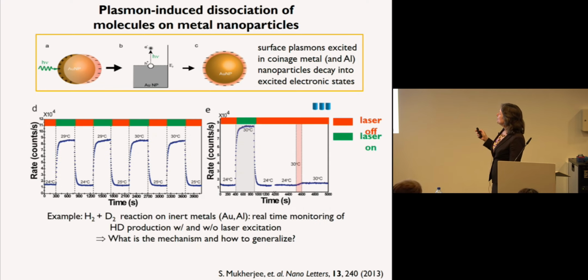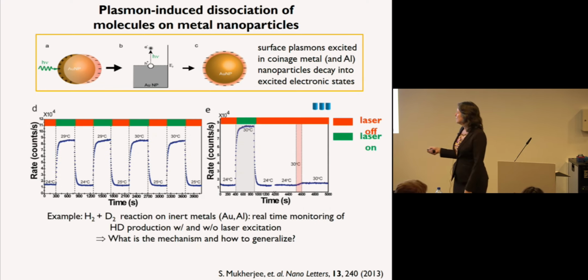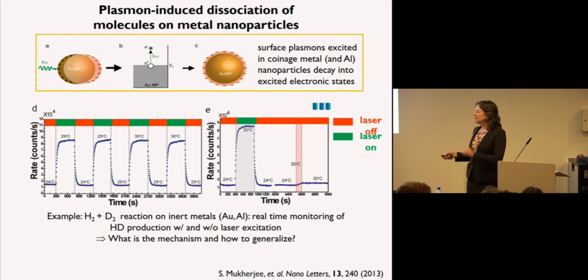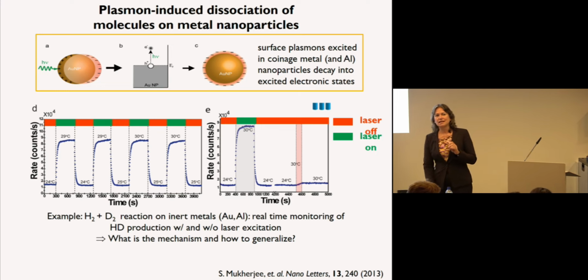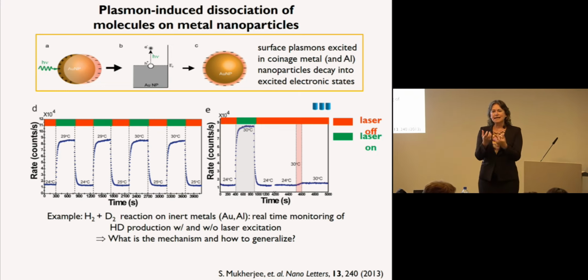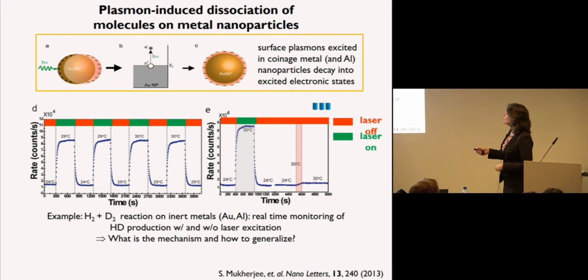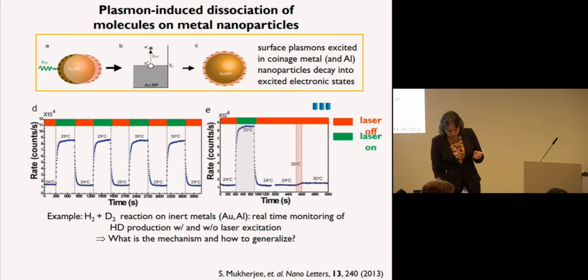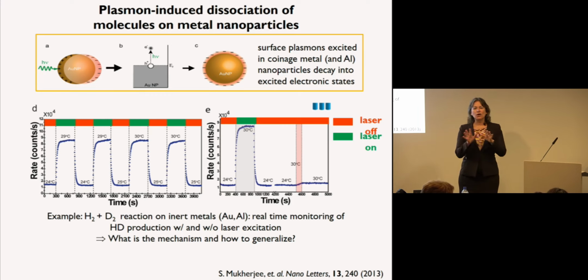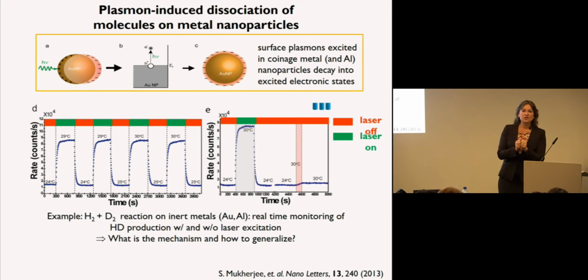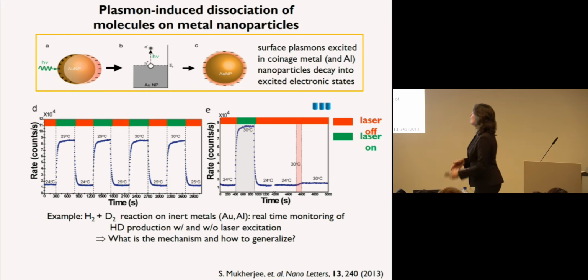This shows an example of the experiments reported in this paper, a particularly interesting example to prove that these excited electrons are doing the chemistry. It takes a mixture of H2 and D2 and shows that when you turn on the light, the green, you get an increase in the rate of production of HD. Why is that a critical point? Because if you didn't have the light and just had H2 and D2 in the dark, you would not see this mixture at all, because hydrogen does not dissociate on gold. It's only in the presence of the light that you see this increase in the rate, and if you turn off the light, the rate goes back down.